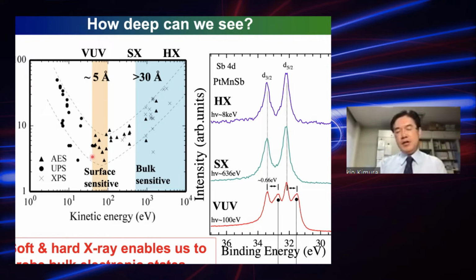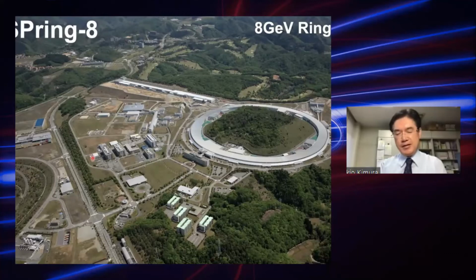On the other hand, the cross-section of photoelectrons decreases very much with increasing photon energy. That means it is almost impossible to do hard X-ray photoemission using the conventional X-ray source, which is typically used for X-ray diffraction. Therefore, we have to choose the brilliant synchrotron radiation, which can be provided by a large facility like SPring-8, shown here.